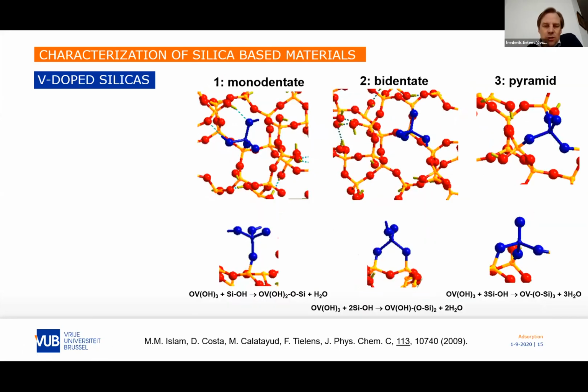The first study that we did is the grafting of vanadium oxide, vanadium 5 oxide monomers, grafted on the silica, which found a lot of applications. I won't go into details, but we were especially interested in the structure. What is the geometry of this kind of sites, and how does it evolve during the reaction or as a function of temperature? So we can graft this entity, vanadium 5 here, which is an oxide, and we have also put some hydrogen atoms, so you have hydroxy and oxo groups. You can bind it with one bond or link, two, and three. As you see, it also has an effect on the OH groups on the side, and in fact we see that it is clearly dependent on the temperature and hydration.